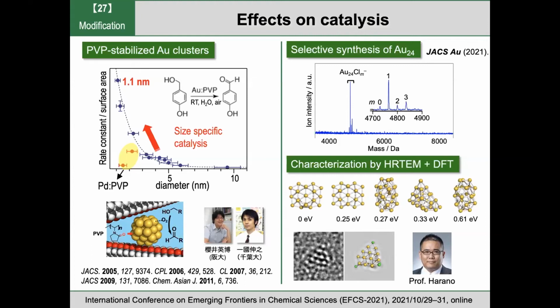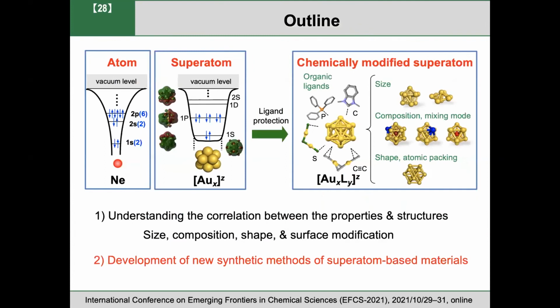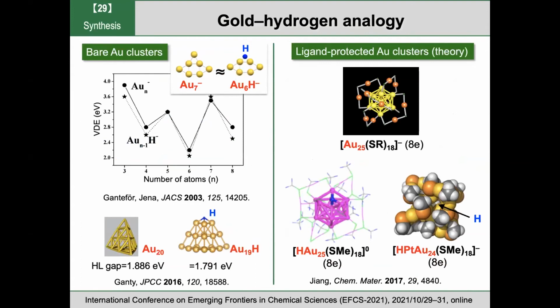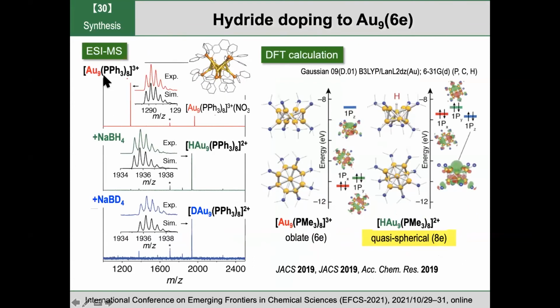Okay, the last topic is the development of new synthesis of superatom-based materials. In previous studies, we know that hydrogen and gold behave similarly, so hydrogen mimics gold. So we tried to dope hydrogen into gold clusters. We can dope a hydrogen atom into this Au9 cluster, because at the center there is a naked gold atom, so we can dope one hydride, H-, species into the center. Then we can detect such species. If we calculate the electronic structures after hydride doping, the core becomes more spherical and the p orbitals become degenerate, so it becomes a quasi-spherical system.